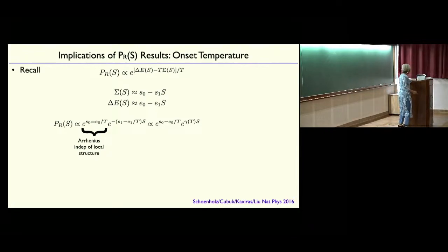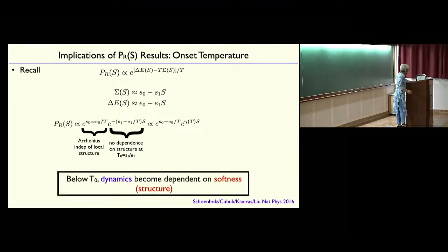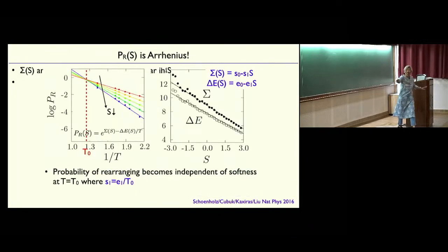Then there's this term that depends on softness. That's the term where, remember, we have roughly exponential dependence on softness at a given temperature. That's this coefficient here. But you look at this coefficient, and you see, aha, there's a temperature at which this becomes independent of softness, where this coefficient is 0. That's S1 over E1. What is that temperature? That's exactly the temperature that you guys were pointing at. This is where the probability of rearranging is independent of softness. It's the same for all softnesses. And what is that temperature? That temperature is the onset temperature.